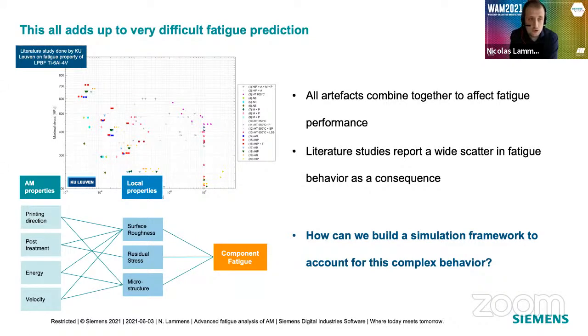And what we know is that in order to be able to predict fatigue life, actually we start from the AM properties. So things like printing direction, post-treatment, energy, velocity, and all those properties affect the local properties. So not the global properties, but actually very local properties like surface roughness, residual stress, and microstructure. And all those local properties then finally come together into the final component fatigue life. So predicting component fatigue means taking into account a lot of influencing factors. And that means that we need to build a model that can account for all those factors.